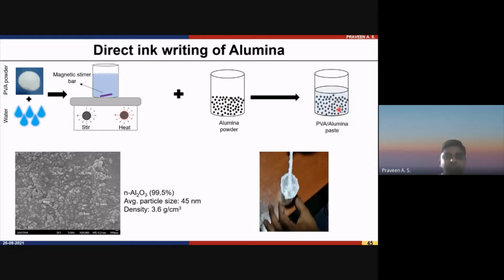Now the ceramic particles will be uniformly distributed in that gel. Here we have taken different compositions, 50% volume of alumina as well as 55% volume of alumina. As I told, the literature shows that we have to choose 50 to 80. I have not tried beyond 55 because I would have to apply higher pressure, and proper extrusion of the slurry is not taking place beyond that. These things you have to find by trial and error. So I have made the slurry as shown in the figure.